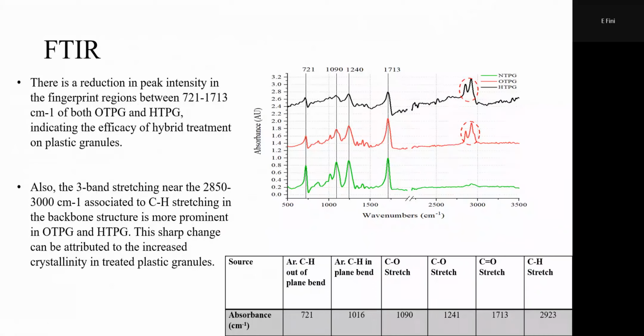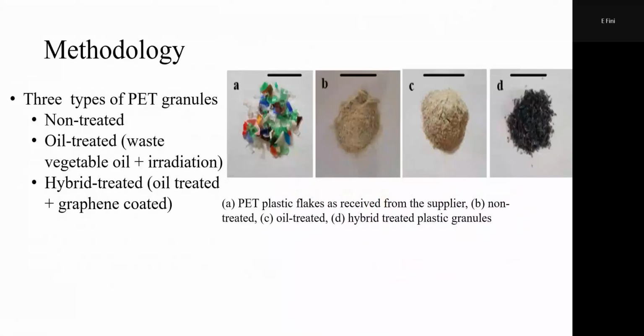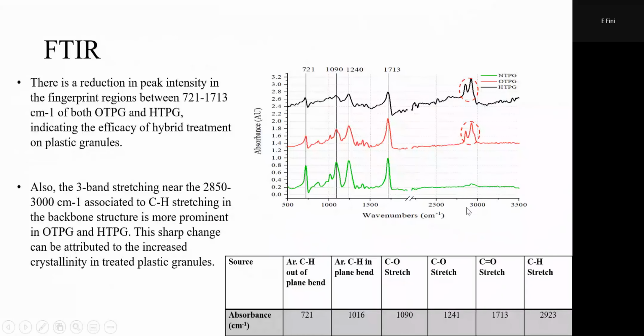I wanted to tell you, right, in this case, B and C are different. How can I tell you B and C are different? I need something to measure. So what did I measure? Here the green is the non-treated and red is treated. When I use FTIR, Fourier transform infrared spectroscopy, here you can see with the FTIR, the peaks in the dashed line appear that did not exist in the green line. So I can tell you for sure red and green are not the same.